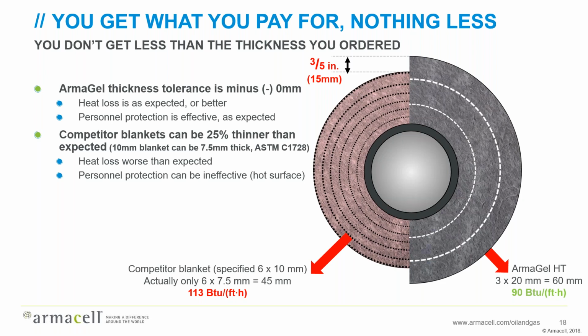That's substantial. That changes your expected heat loss from 90 BTU per foot hour to as high as 113 BTU per foot hour. Imagine if you set the personnel protection temperature based on 60 millimeters of aerogel blanket, and suddenly you find that you have 45 millimeters on there. Suddenly you've got a dramatic increase in the surface temperature, and that's a burn hazard.